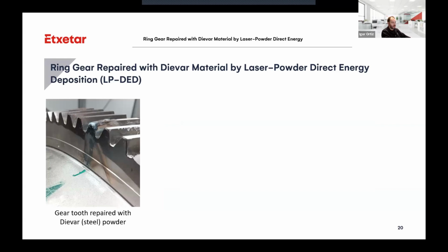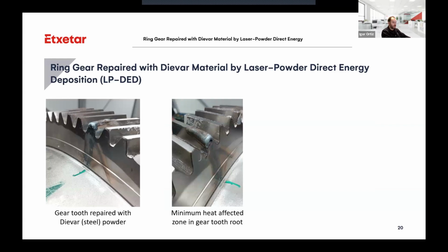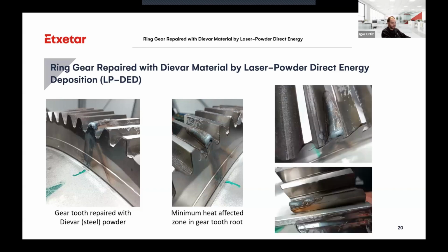This is one tooth that has been repaired. We have been taking into account to affect minimally the root of the gear tooth, and these are some examples of the repaired gear tooth. The material that has been used is Dievar powder. It's a high strength steel. Why we have used this material is because, as I mentioned before, the powder comes without pores. It has a hardness between 52 and 58 Rockwell C, so high hardness for a gear tooth. And also in parallel, Aaron has taken the data of fatigue curves of the Dievar. So it's working well in different loads.